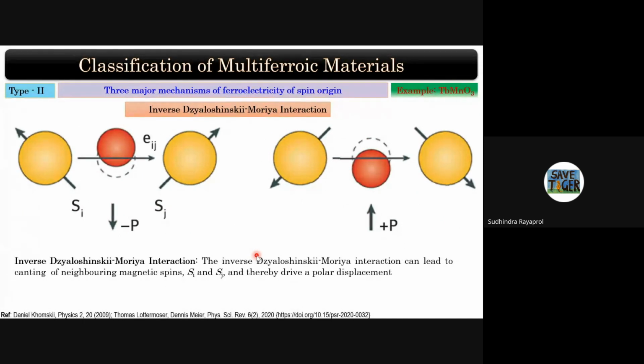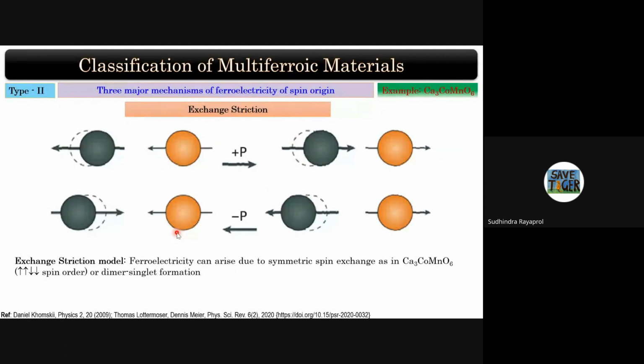In type 2 multiferroics, you can have what is known as the inverse DM interaction. Because of this DM interaction, you can have interaction between alternating spins, which can actually give rise to displacement of the ion. Basically, in the case of this DM interaction, you are talking about the canting of the spins, or you're looking at spiral structures in magnetic structures. You can have exchange striction also, like in the up up down down configuration, which we see in Ca3CoMnO6. Because of this kind of movement of spins towards each other or opposite to each other, you can get this polarization.